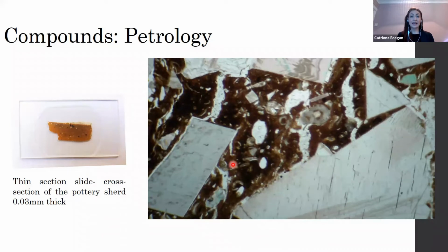And then this is analysed underneath a microscope, and it allows somebody who's an expert like Claudio to identify what all of the different components in the potsherd are. So, for example, these very angular white inclusions, these are calcite fragments, and it looks like they've been crushed because of this very sharp angular shape that they have. Generally, whenever you get natural inclusions, the edges tend to be a bit softer, a bit rounder, because a bit of erosion has happened within the landscape, whereas these look like they were freshly crushed and then added to the clay mix.